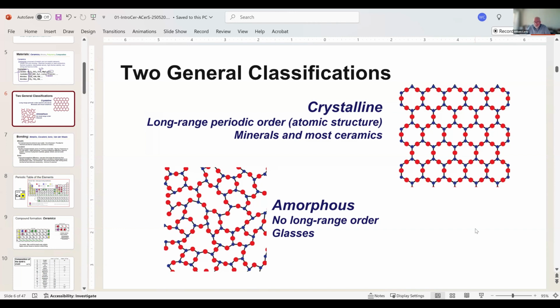Amorphous materials have a random network, no long-range order, no repeat units, as it were. And that structure is the structure of glasses. We call it amorphous, and we call them glasses. And they offer us a much different melting behavior, much different material properties overall in general, but they still exhibit the things that we like and don't like about ceramics. They tend to be high strength. They tend to be brittle, which we typically don't like. The other thing is, though, that they can have almost an unlimited range of compositions. So that gives us a lot of flexibility.